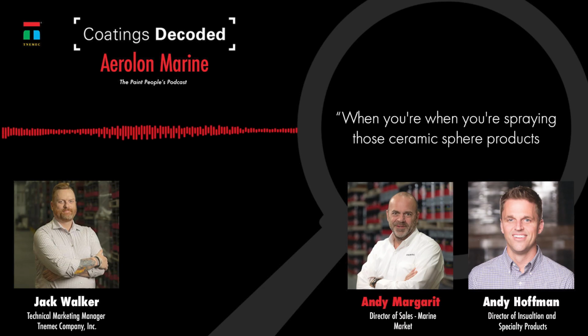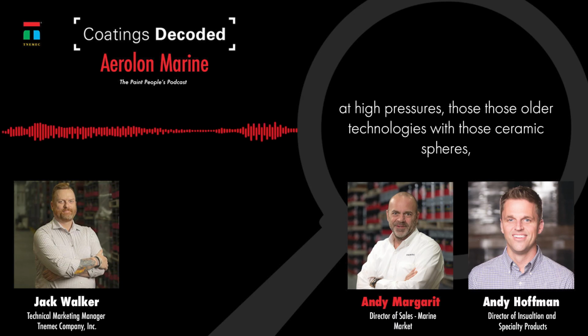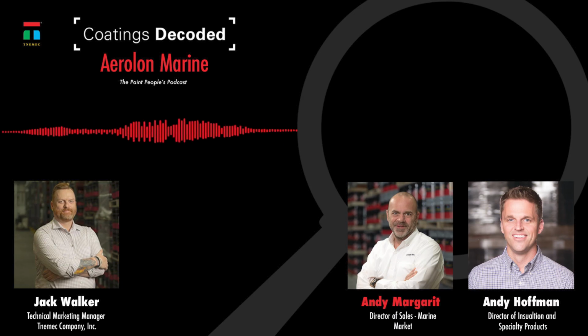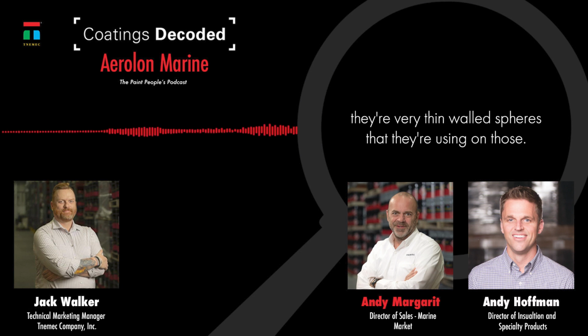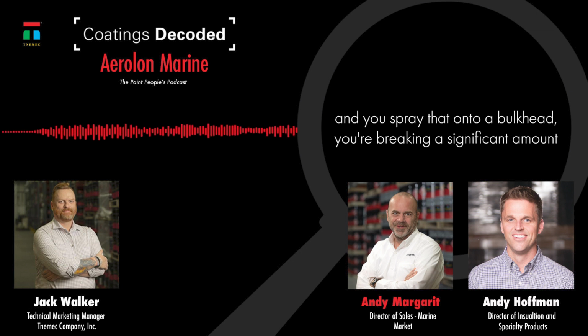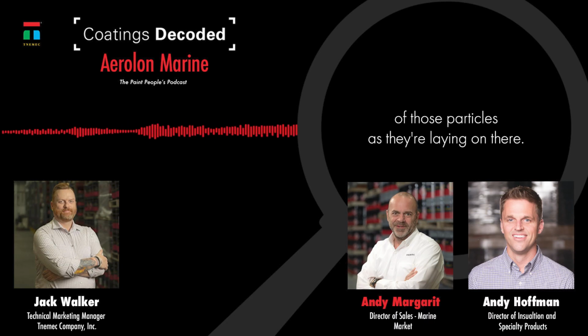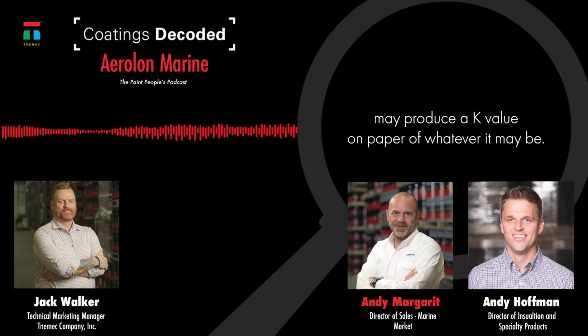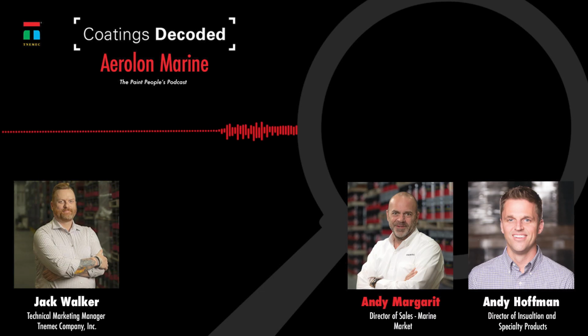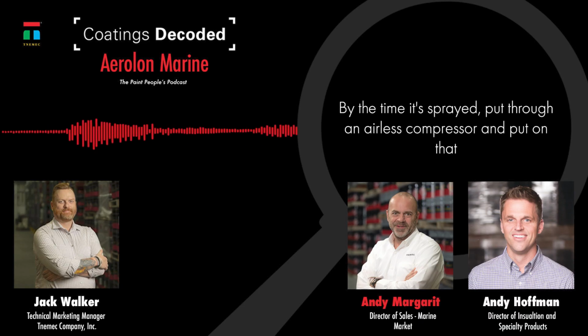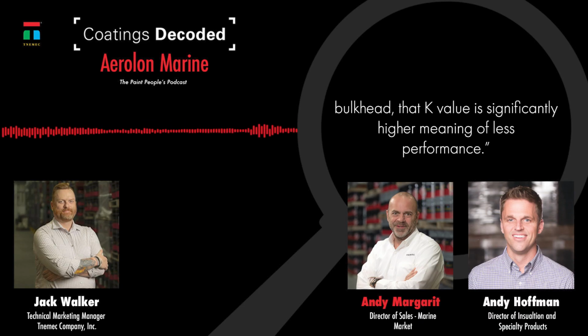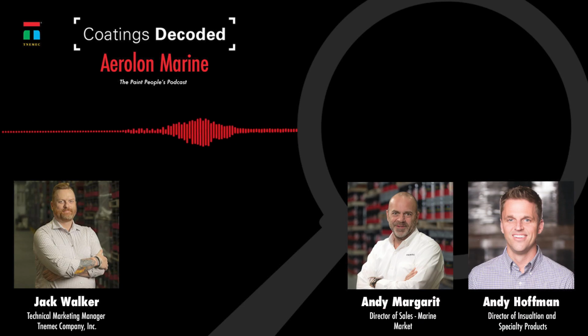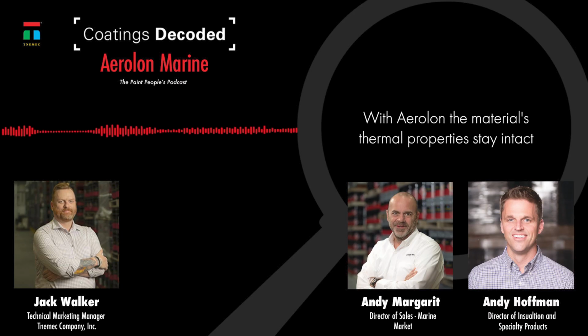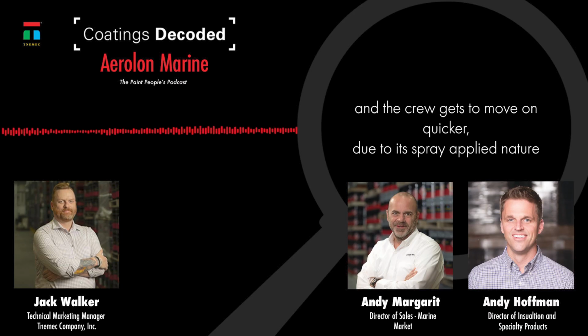When you're spraying those ceramic sphere products at high pressures, those older technologies with those ceramic spheres, they're very thin-walled spheres that they're using on those. So when you put them under pressure on an airless sprayer and you spray that onto a bulkhead, you're breaking a significant amount of those particles as they're laying on there. So where a coating like that may produce a K value on paper of whatever it may be, by the time it's sprayed, put through an airless compressor, and put on that bulkhead, that K value is significantly higher, meaning less performance. With Aerolon, the material's thermal properties stay intact, and the crew gets to move on quicker.